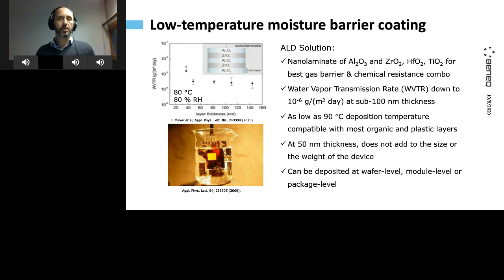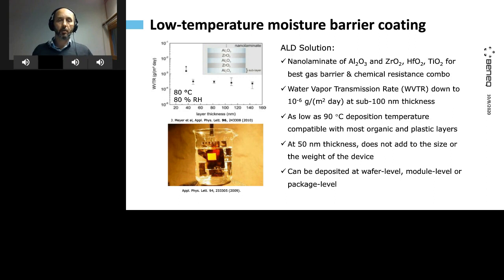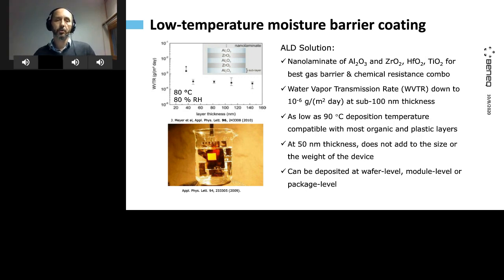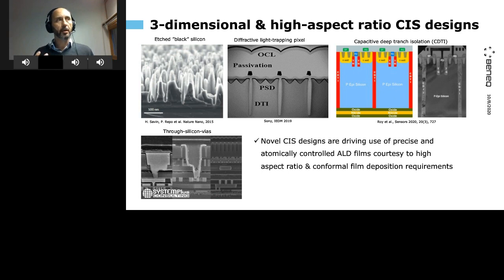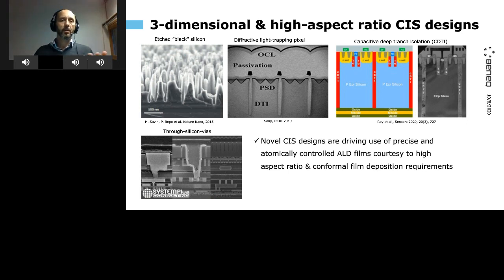This is compatible with most organic materials, meaning you could do these coatings at the wafer level, at a later stage in the module level, or even during packaging. With more time, I would also like to mention designs where you're looking at a higher surface area of silicon — either by generating diffractive light-trapping pixels or using black silicon, a more futuristic topic. With these structures, as well as deep trench isolation, what you really need is a conformal coating technology to enhance the properties of such devices. In the same class in terms of aspect ratio is through-silicon via for 3D integration, where ALD is obviously being used.